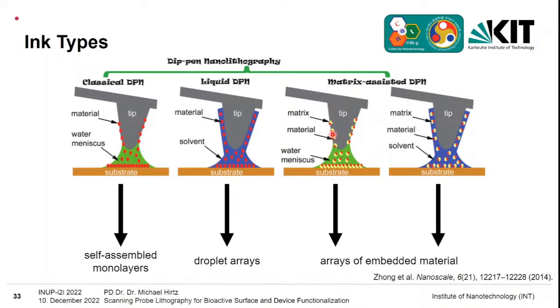Then you would say, okay, you have a material that you want to transfer, and you have a matrix that's maybe carrying the material, or a solvent, and this matrix helps with getting stuff down to the surface. This is, for example, very helpful if you want to deposit nanoparticles that would maybe in themselves rather stick to the tip. But if you combine them with other materials like glycerol or a more viscous ink that can draw them to the surface, then you can also write these.